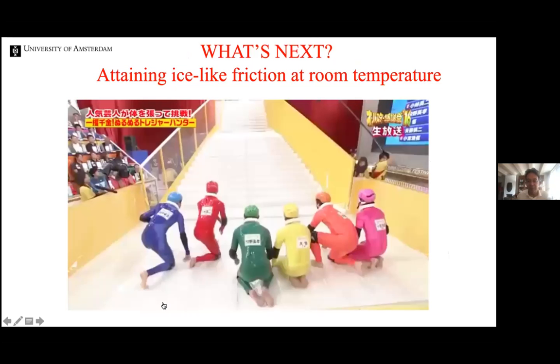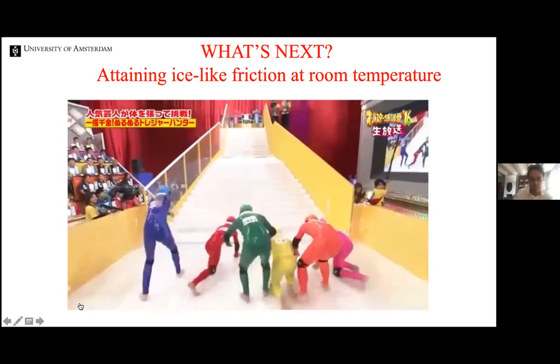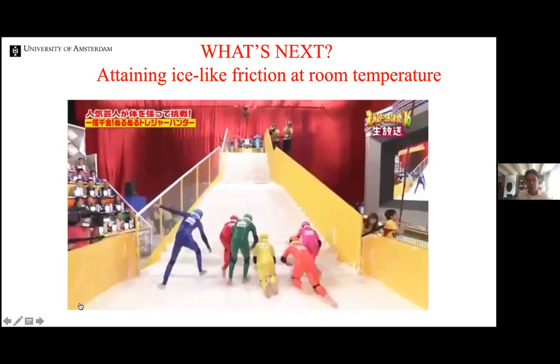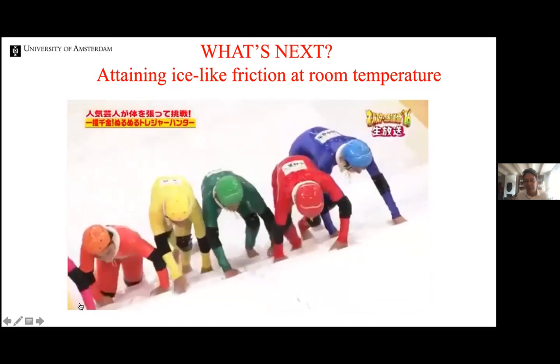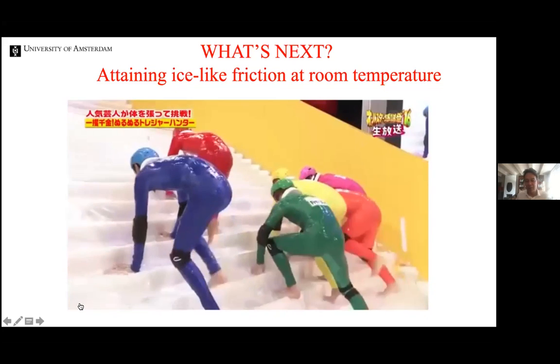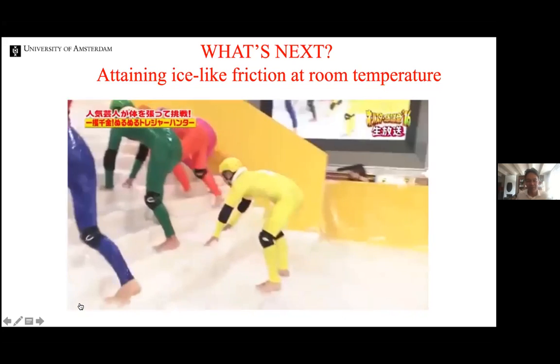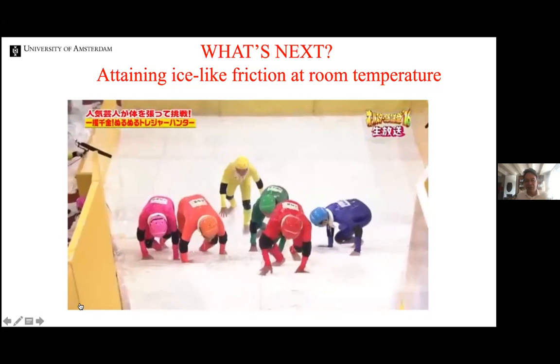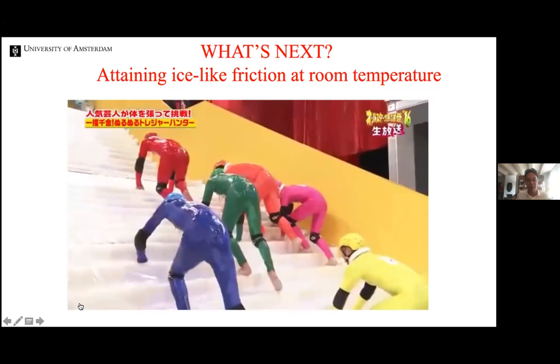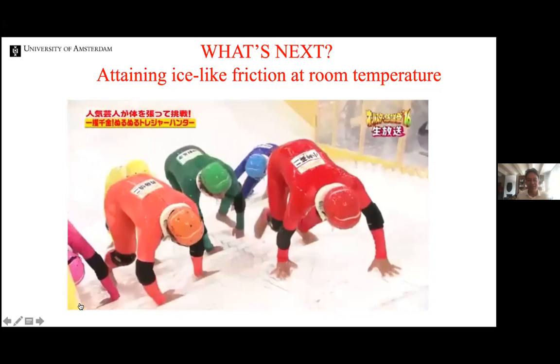What I want to end up with is what you would really want to do, of course, which is to have ice-like very slippery surfaces at room temperature. And there's one way in which this can be done, and we're actually investigating this also. This is a Japanese game show, where people put a high molecular weight polymer solution, an aqueous high molecular weight polymer solution, onto this stair, and this leads to a surface that is almost or quite as slippery as ice.